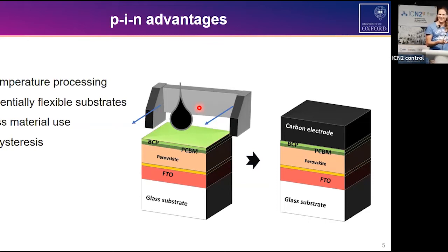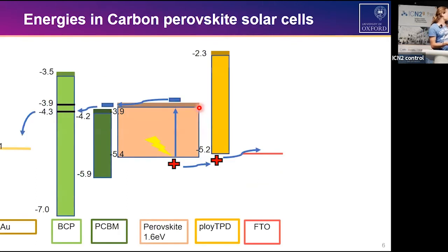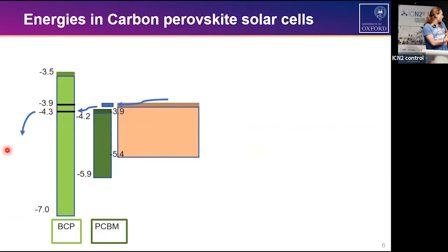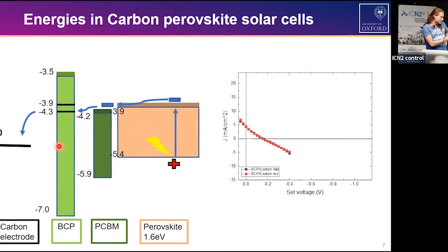So far the theory. When I first tried that, just to give you a quick overview, this is my stack. The reference would be gold with a work function of minus 5.1 eV. I will focus on the N side in PIN, because that's the side in direct contact with the carbon that we're going to introduce. And carbon has a minus 5.0 eV work function, so it's very similar to gold. That's why there was the initial thought that it would work.